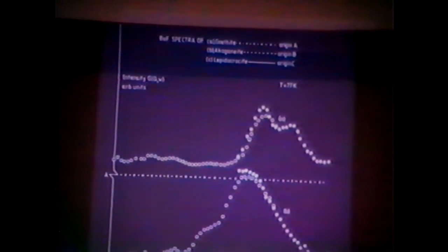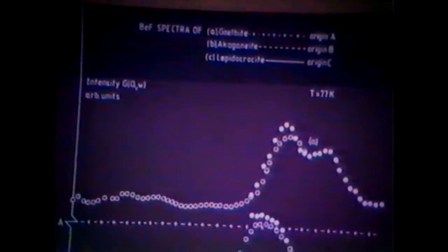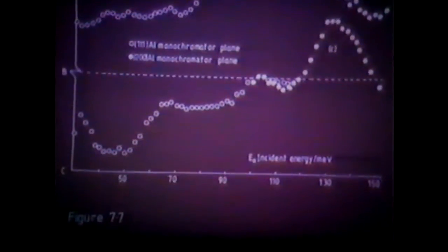And this actually was confirmed by infrared. The initially ice-like structure adsorbed on the surface of maghemite has now changed to goethite. And goethite is formed in the outer layers. We estimate about 1.5 monolayers, basically. So the neutron technique can be quite useful in showing how changes occur on the surface.